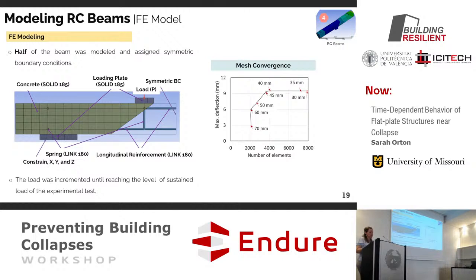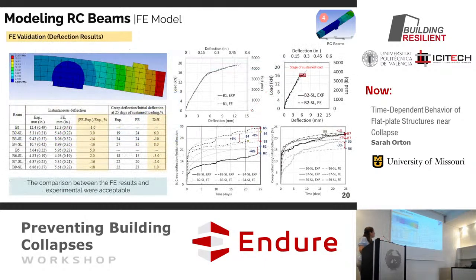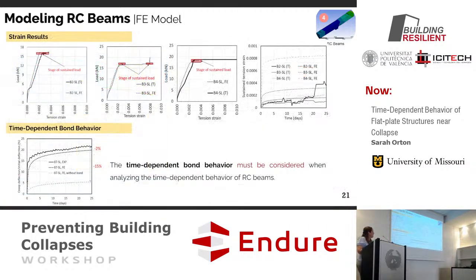And so we did models of some reinforced concrete beams. I'm not showing those tests here, but I have a paper out about the beam test, just about 4-foot long beams, about that big, about that size and cross section. Modeled those beams, compared it to the experimental data, and the differences are fairly acceptable for this type of work, especially under sustained load. Then we also looked at the strain and the time to failure, and pretty decent work.